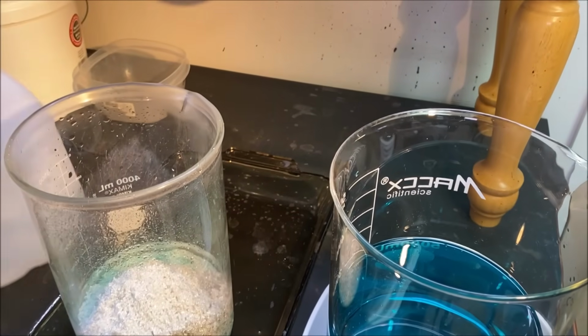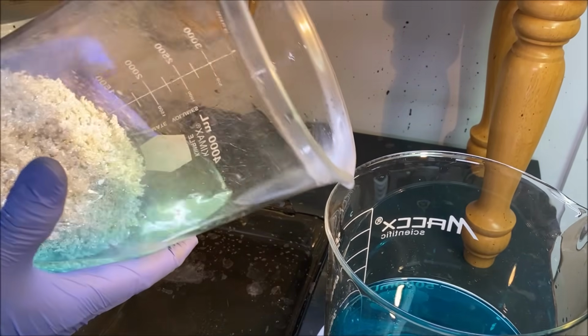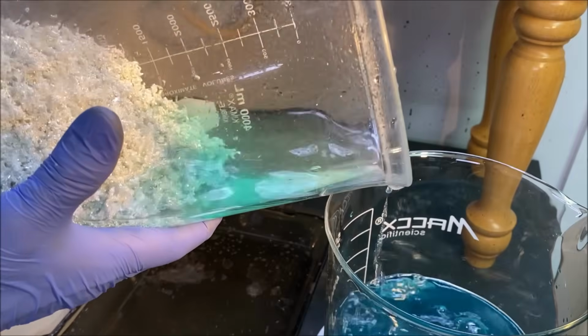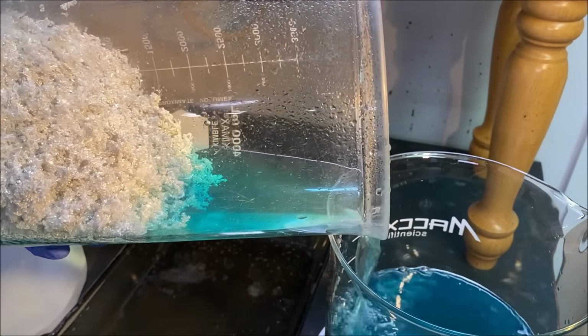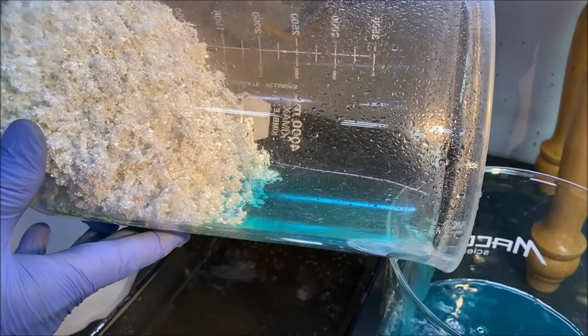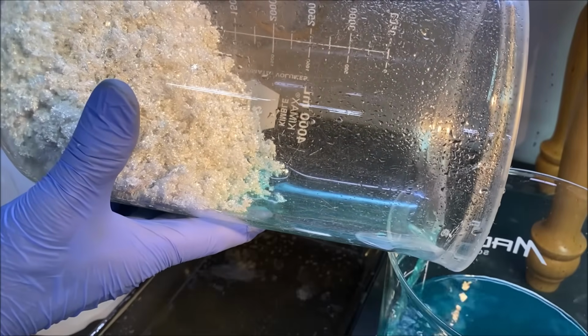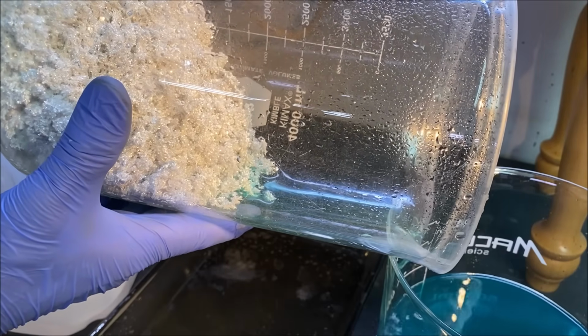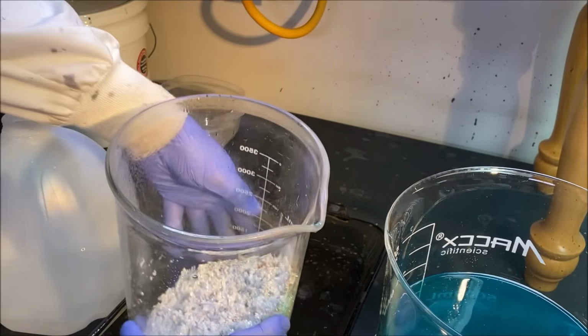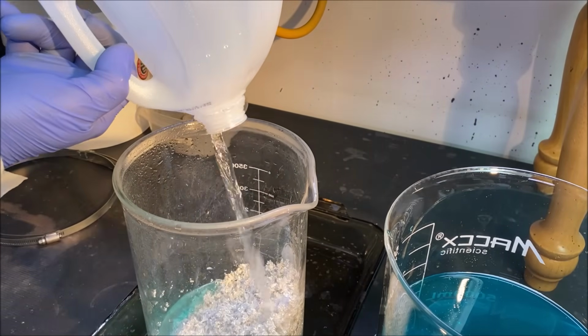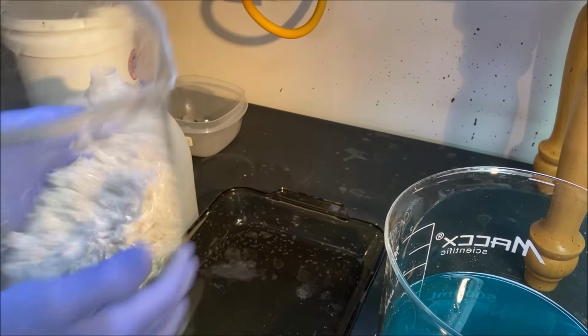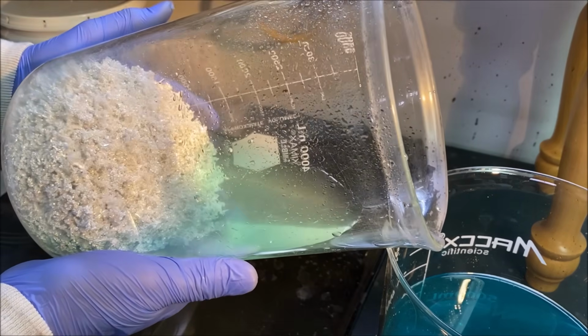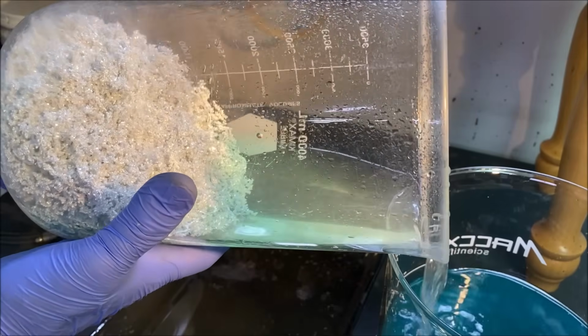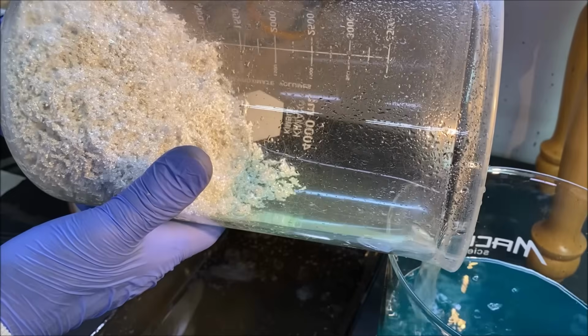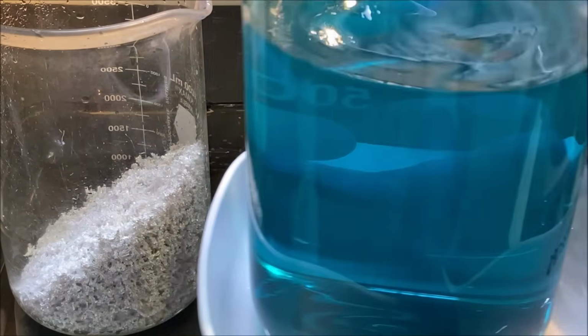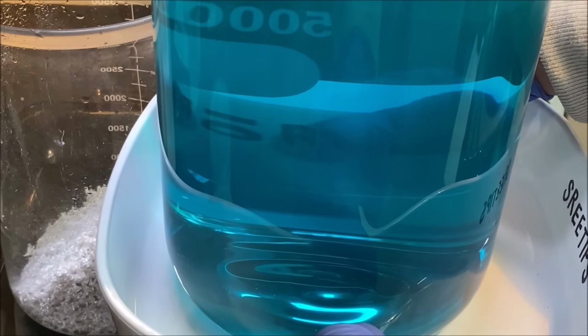Rinse this off with a little bit of distilled water, and we'll add this rinsed water to our spent electrolyte beaker. This silver, man, is beautiful. There's at least 2 kilos here, probably more than that. I'm going to take this electrolyte now, and we're going to put this in a fume hood and cement the silver out of this solution so we can recover it.